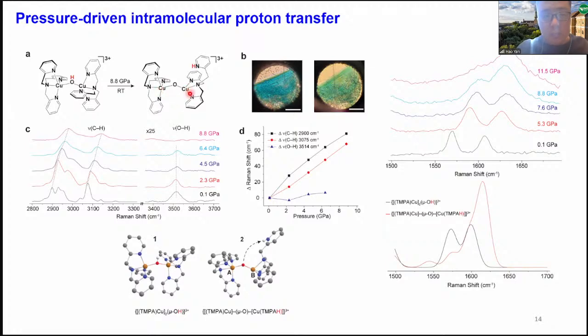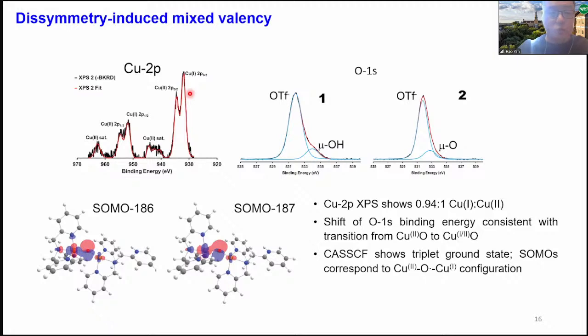We break the symmetry of the molecule, and that broken symmetry leads to a mixed valency. We start to see that we have a mixed copper-1 and copper-2 species with a ratio of 1:1.